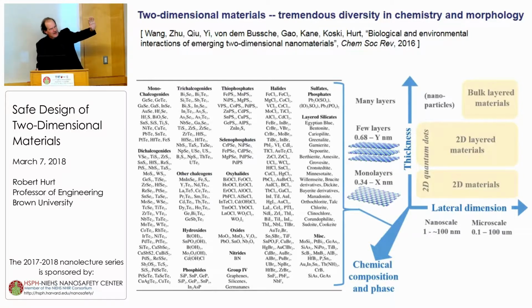And so we've got all this chemical diversity in this material family, but it's also crossed with this morphological diversity. If you look at the 3D plot on the right, we have chemically diverse materials, but they also vary in terms of their layer thickness from monolayers to few layers, all the way up to bulk materials. And then in lateral dimension, we have some materials that are nanoscale in the lateral dimension, and these may, in biological systems, behave in a way that's not dissimilar to particles, but then they can be grown all the way out to microscale dimensions, and these are materials with enormous aspect ratios that are rare in nature, and we can expect some unique biological interactions from.